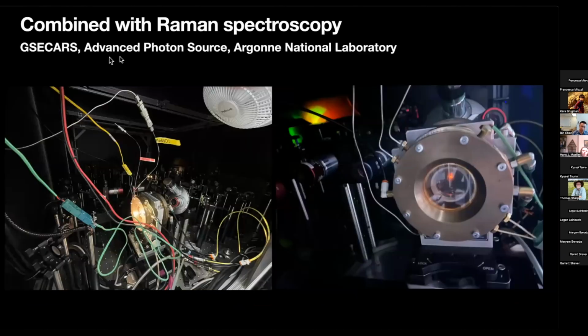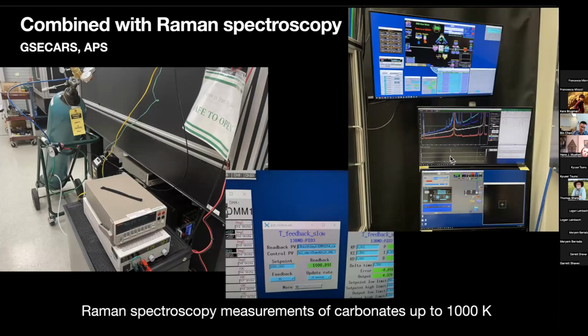And we also tested in the Raman lab at the GSECARS. We performed some experiments by collecting the Raman spectrum of some carbonate at high pressure, and we observed decomposition of those carbonates at high P-T conditions. This experiment was performed up to 1000 Kelvin.